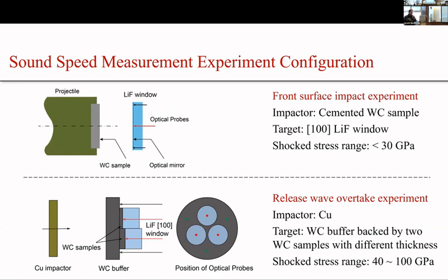The next set of experiments that we did is to measure the sound speed in the shocked tungsten carbide sample to get the evolution of the elastic moduli. There are two configurations that we use in this set of experiments. One is called the front surface impact, and the other one is called the release wave overtake experiments. The first one has a more accurate measurement, but the stress level achievable in this configuration is limited to less than 30 GPa. So for stress higher than that, we need to use the overtake configuration.